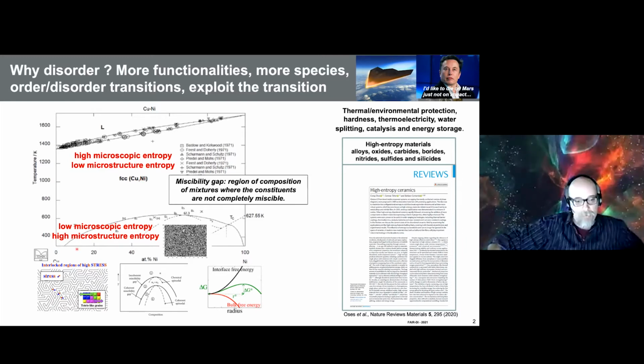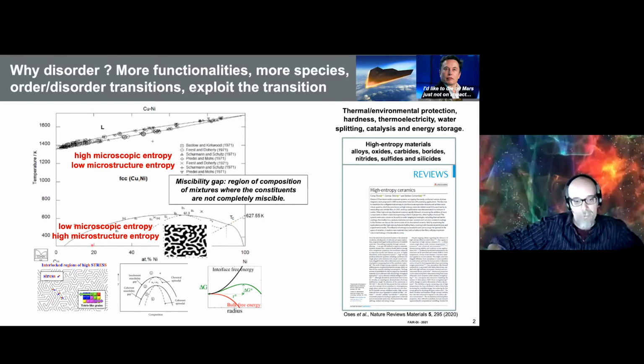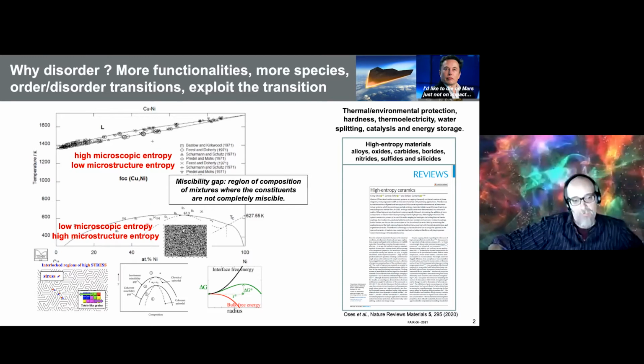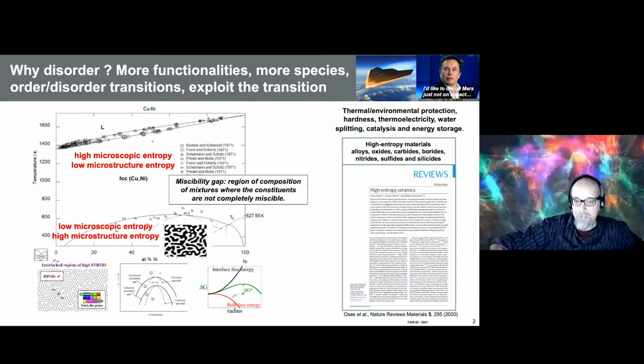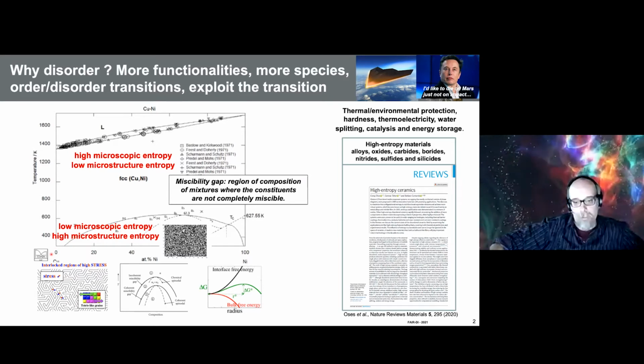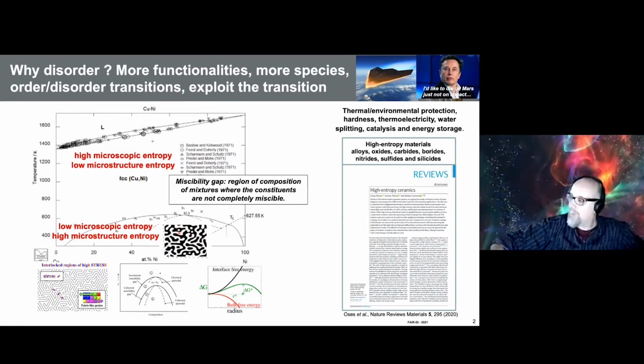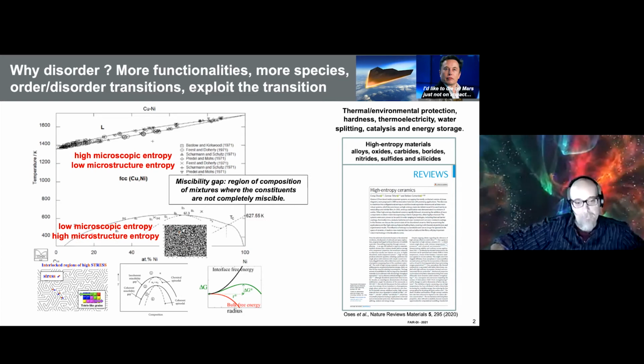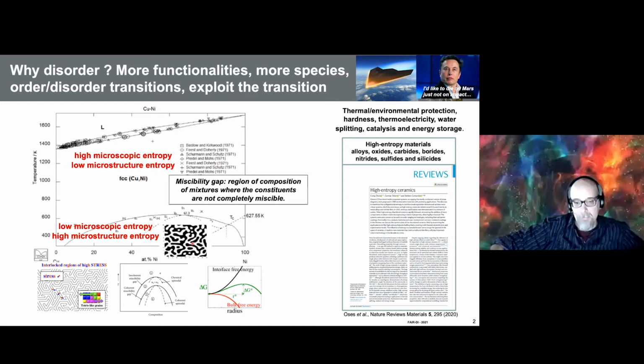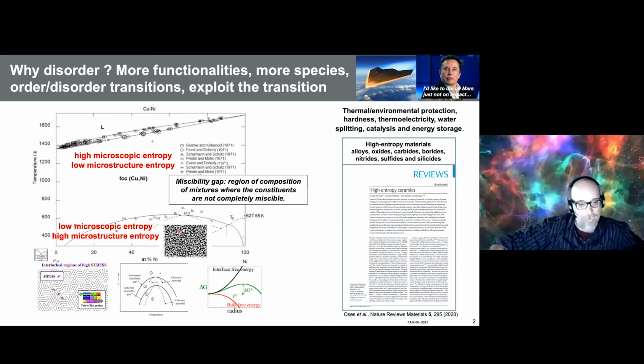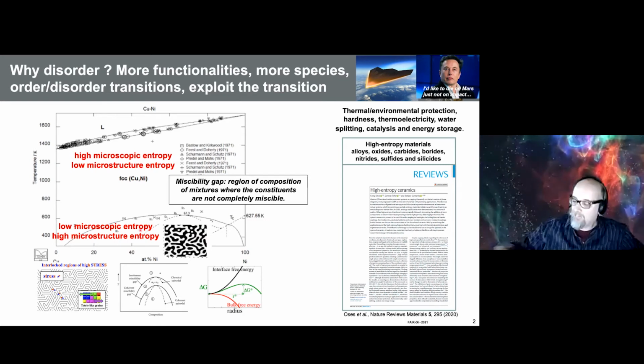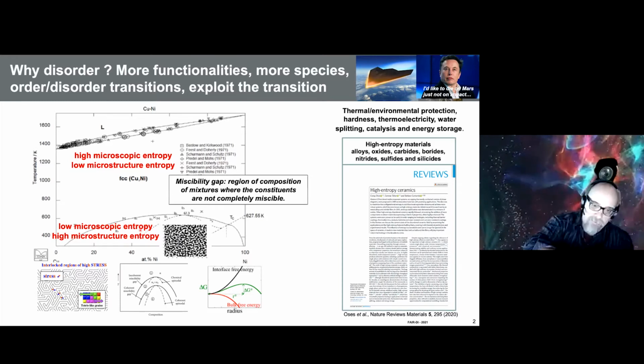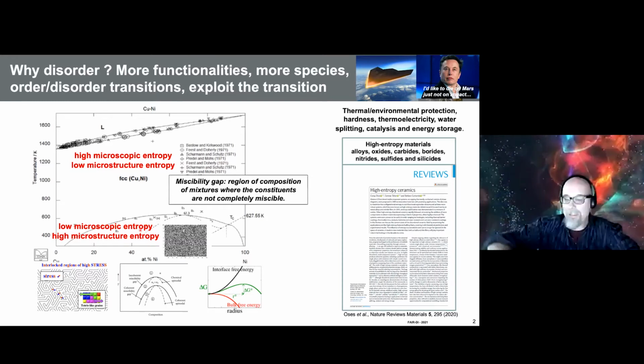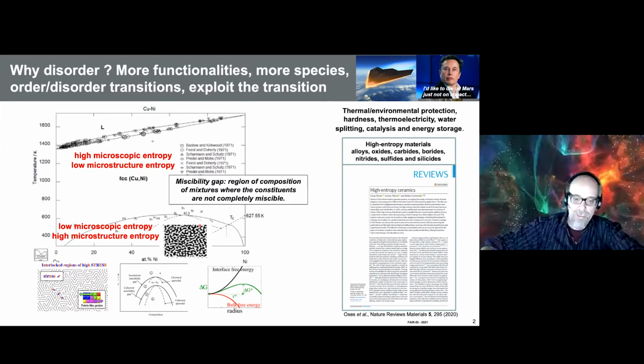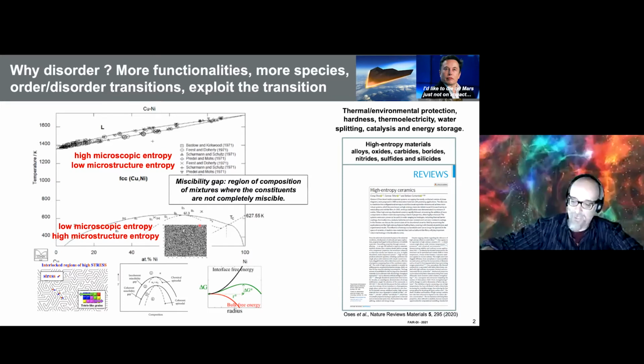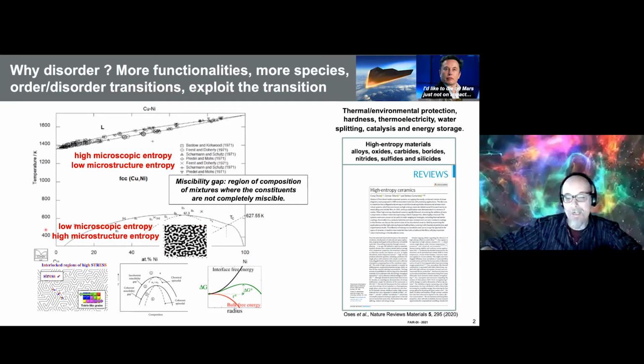If you decrease the temperature, you see that you have this line. This line is called the miscibility gap, and under this line you have what is called a low microscopic entropy. Think about it: if copper were black and nickel were white, then you would have some sort of phase separation, which can be binodal or spinodal, depending on which part of the phase diagram you are. And then you have a low microscopic entropy, because copper likes copper, nickel likes nickel, but at the same time you have this kind of spaghetti organization, which is some sort of microstructure, which actually gives you high macroscopic entropy.